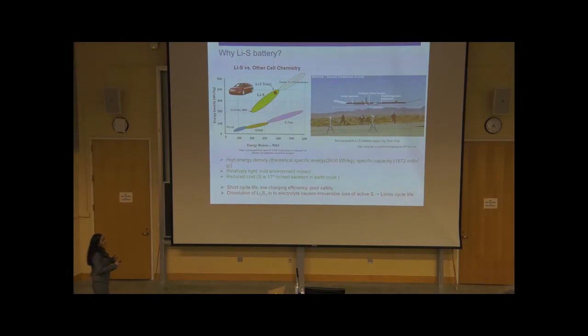They can also be much lighter because of the low atomic weight of both lithium and sulfur that are used as electrode material in these batteries. And they can be significantly cheaper because of the high abundance of sulfur. And these batteries were used in one of the longest and highest altitude solar powered air flights called Zephyr back in 2008. So they're not new and people have been trying to make them work. The major problem is their short cycle life and their low charging efficiency, which comes through the dissolution of lithium polysulfide species through an irreversible reaction, which results in loss of electrolyte and limits the cycle life of lithium sulfur batteries. And I'll explain this sentence in the next slide.